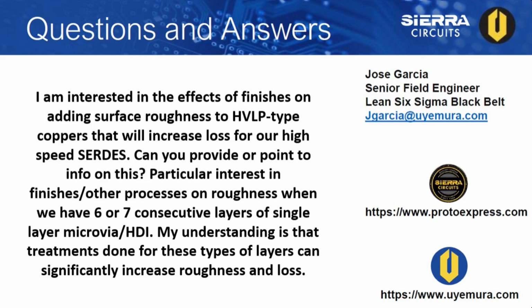So one thing we are looking at is doing fully additive. This gets into ultra high density, but we're looking at embedded trace technology that doesn't use foil; it's fully additive. So you don't use the dendrite structure on the foil, nor do you need the adhesion promoter on the surface. So anyway, we're looking at getting rid of that, but it is a problem.